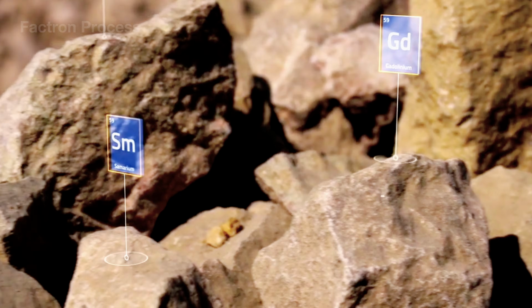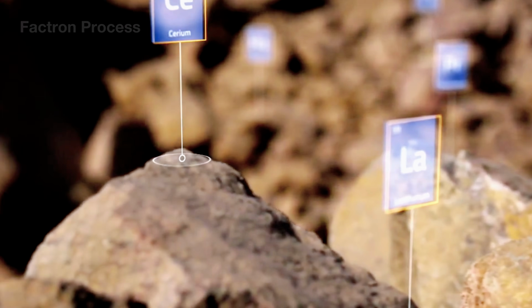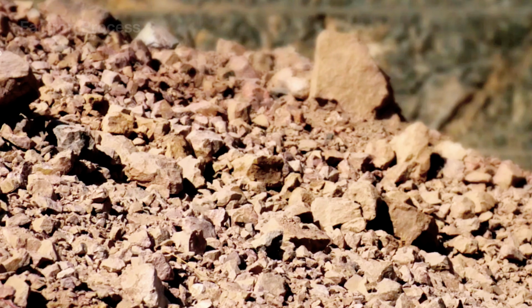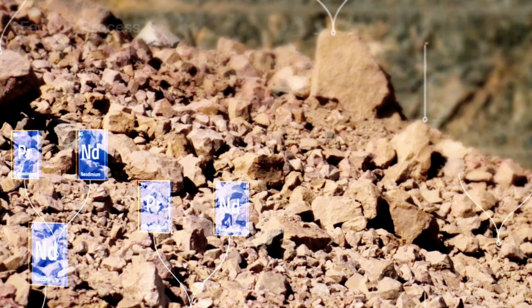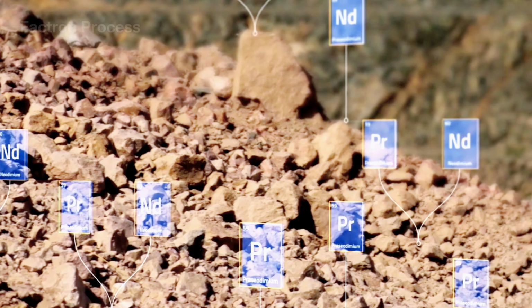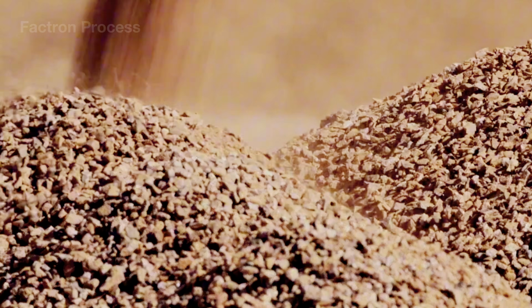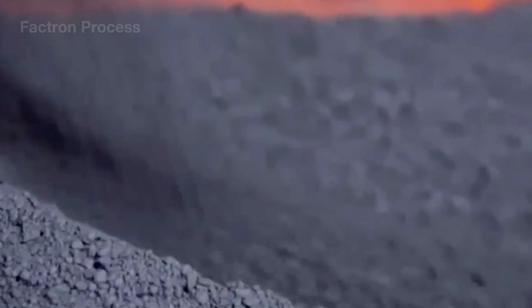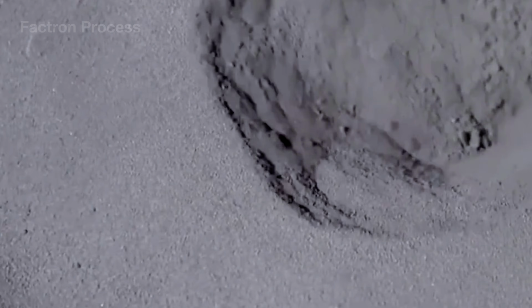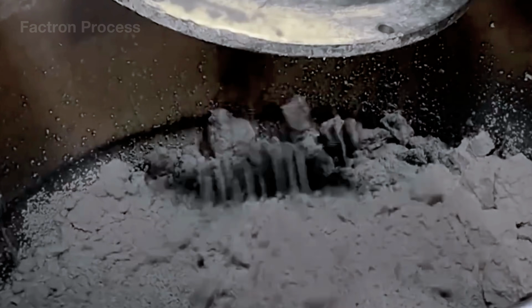The oxide powder is fed into a molten salt electrolysis system operating at approximately 1050 degrees Celsius. A direct current of up to 30,000 amperes reduces the rare earth ions into liquid NdPr metal at the cathode, while the graphite anode produces gases containing carbon oxides. The molten metal sinks to the bottom of the cell, is extracted, and then transferred to a rotary casting device where it solidifies into NdPr plates or ingots for the alloy melting stage.